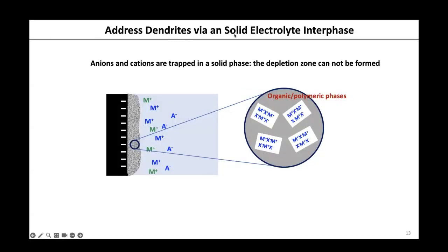Another one is to grow a so-called solid electrolyte interphase. This is something that hugely benefited lithium-ion batteries, and it is arguable that it is due to the solid electrolyte interphase grown on the graphite surface that enabled the commercialization of lithium-ion batteries in the early 1990s. If the electrolyte decomposes on the surface of the electrode, this decomposition layer is like a mosaic, made up of some polymers or organic matter converted from the decomposed electrolyte molecules. And you also have some salt formed. These domains of salt are comprised in the layer. We call it the SEI layer.